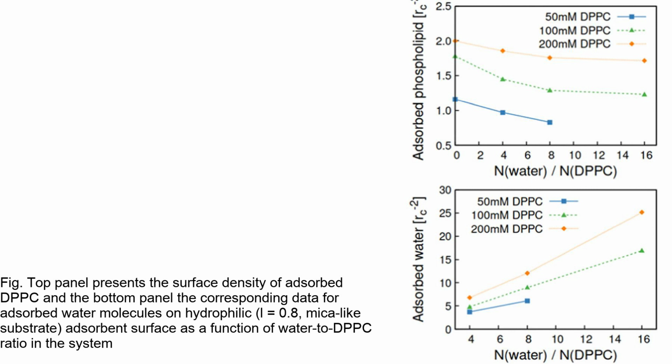The presence of water affects the adsorption behavior. On hydrophilic surfaces, water competes with DPPC for adsorption, resulting in a decrease in DPPC adsorption with increasing water content. On hydrophobic surfaces, water promotes the growth of DPPC aggregates and leads to increased adsorption of both DPPC and water.